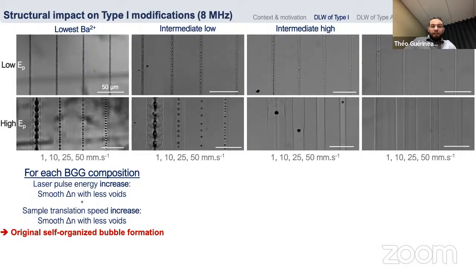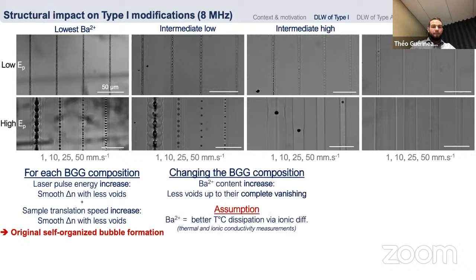We observe a smoother delta N with less and less void, less and less bubbles. As I told you earlier, here we observe the generation of a self-organized bubble, which is kind of original in this case, because what has been published in the past was that type 1 was only an epiphenomenon during the apparition of the bubble. While in this case, it's the inverse. We have the type 1, and during the irradiation, we observe the formation of this bubble. So now the bubble formation is an epiphenomenon in this case.